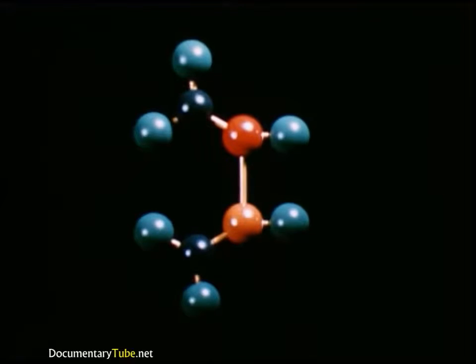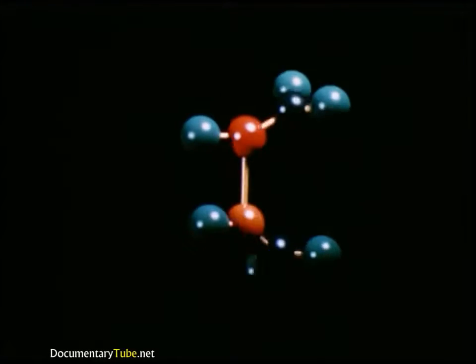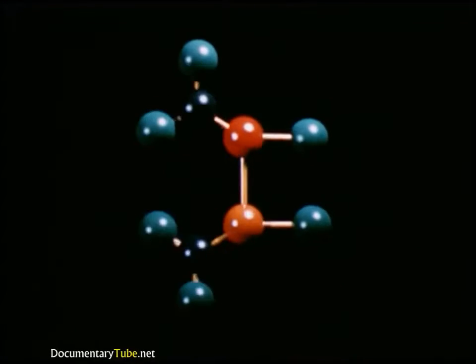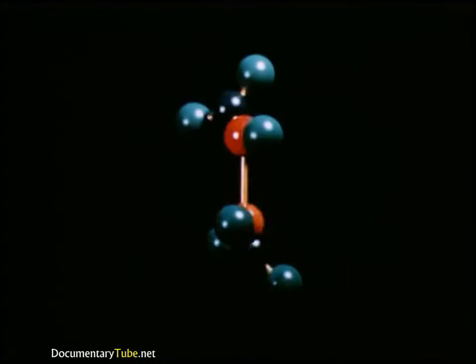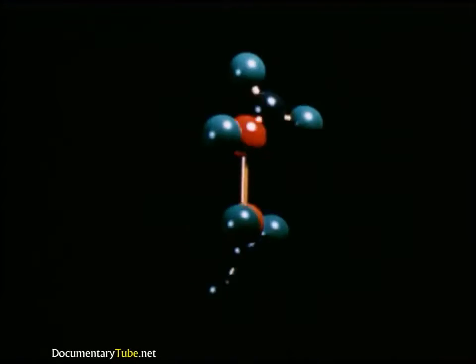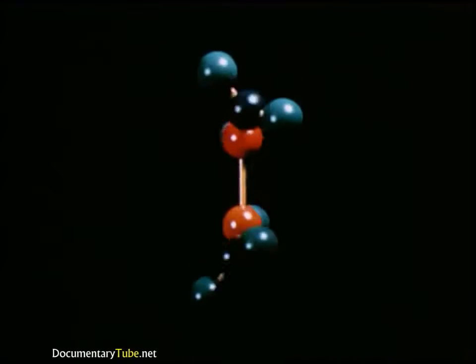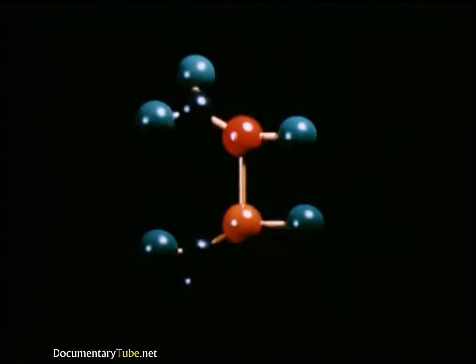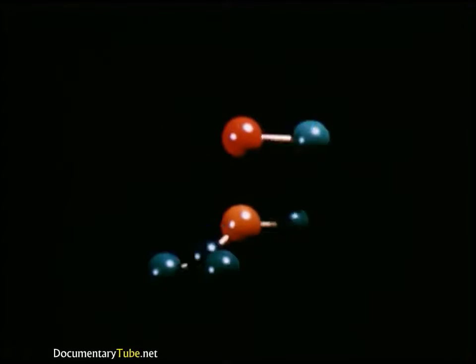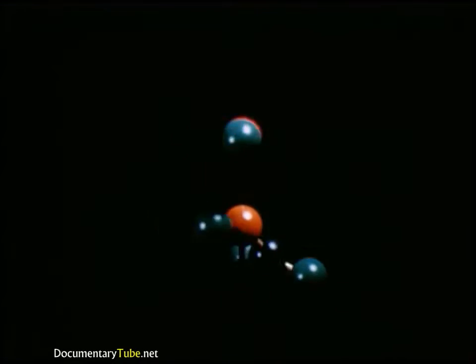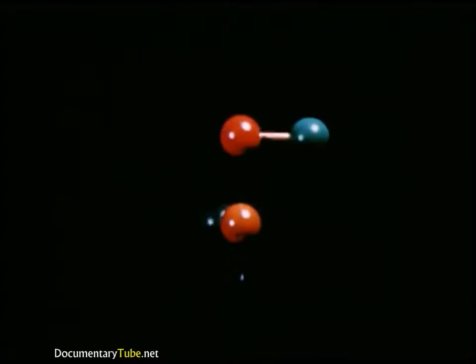The first movements of the model represent activity at room temperature, which is slower than the mineral crystal that actually oscillates in the order of millions of vibrations per second. As heat is applied, the temperature rise causes more rapid movement. When the temperature reaches 1,300 degrees, the carbon dioxide group of the magnesium has gained enough momentum to break its bond and fly off. At 1,832 degrees, the calcium loses the remaining carbon dioxide group. The gas bubbling into the indicating solution forms a precipitate and establishes that carbon dioxide has been released during the heating process.